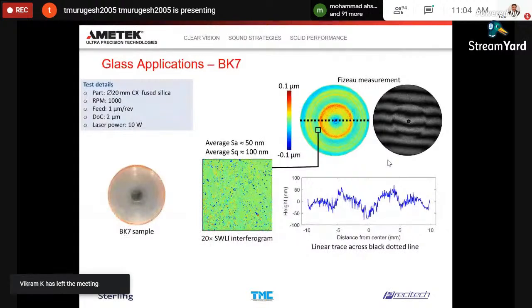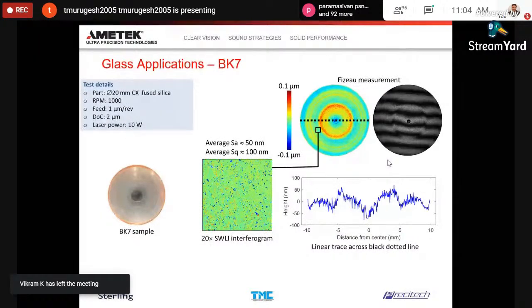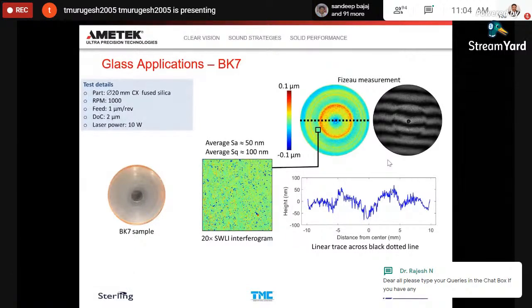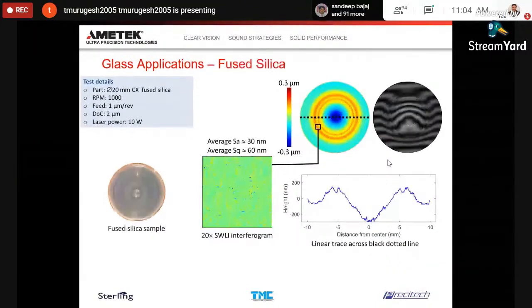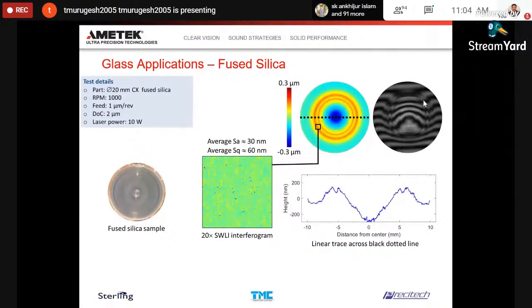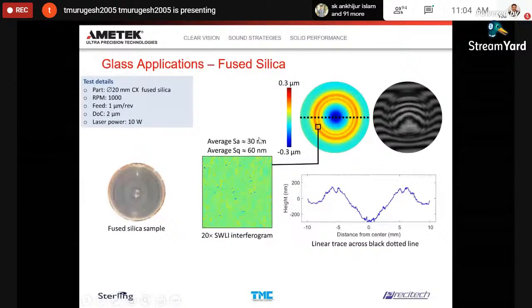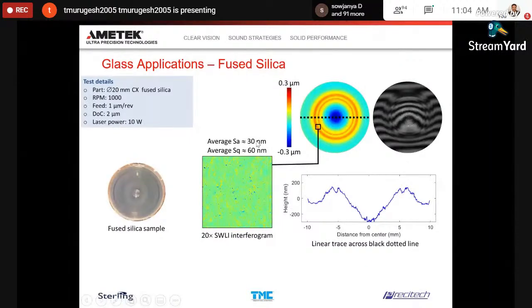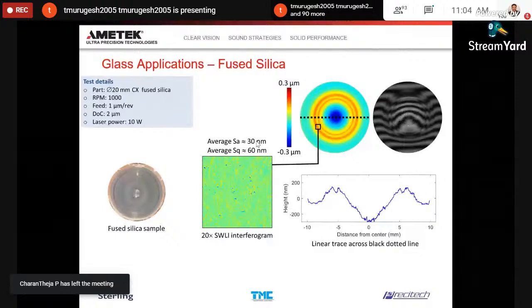So we can also machine BK7 glass. There are some BK7 samples, and with the interferometer we were able to identify what was possible in terms of measuring the BK7 glass after machining with the microlam as well. Fused silica, again, the surface roughness achievable by diamond turning using the microlam was around 30 nanometers. It's good, which makes process setups very simple for these space applications when they wanted to use grinding. Diamond turning has significantly helped them.